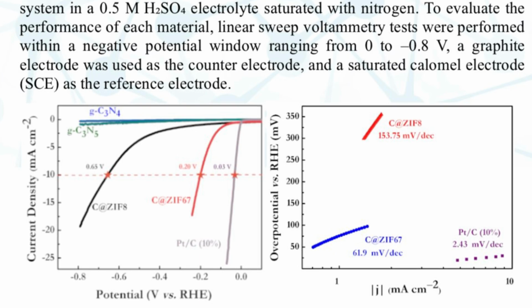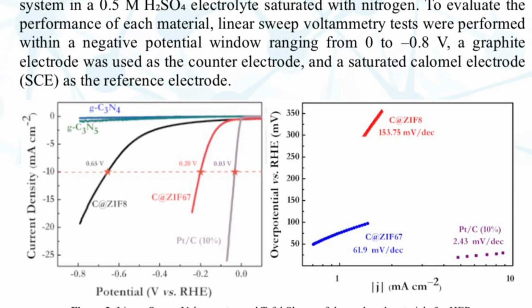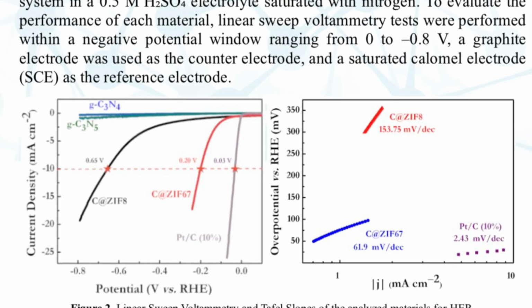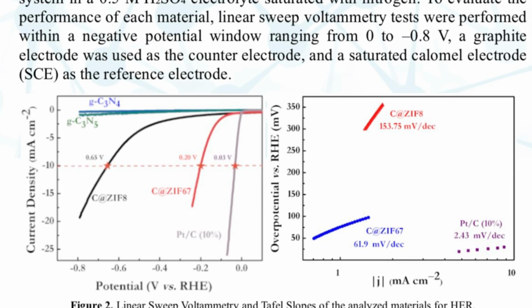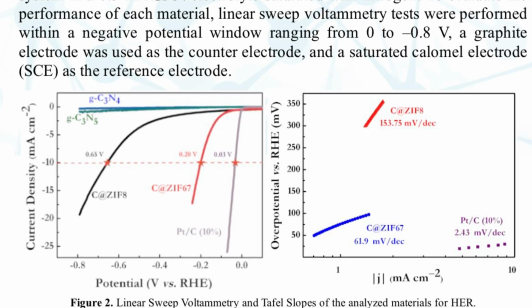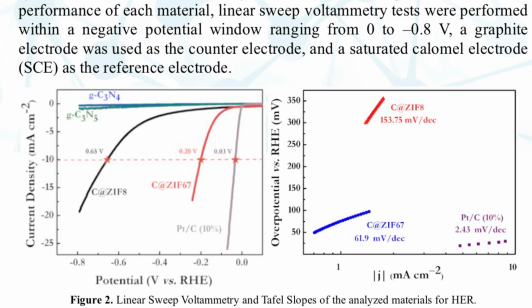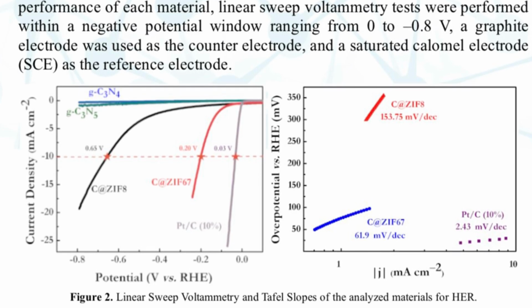reference electrode. The observed trend in the overpotential is that black platinum is still the material that requires less overpotential to start the reaction, followed by carbonized ZIF-67 and ZIF-8, with the graphitic carbon nitrides in the last positions.